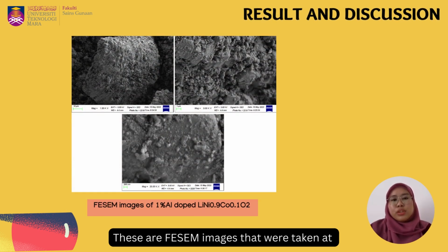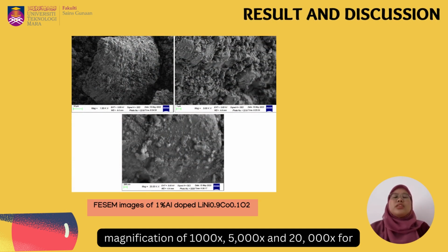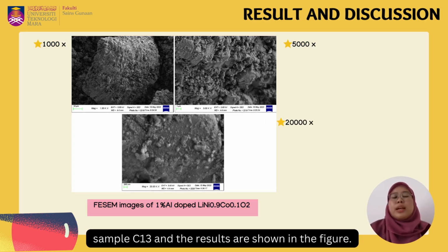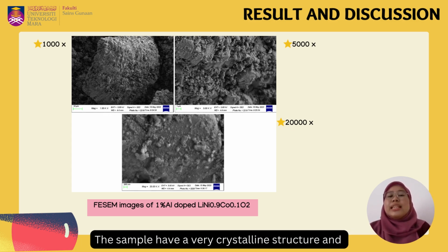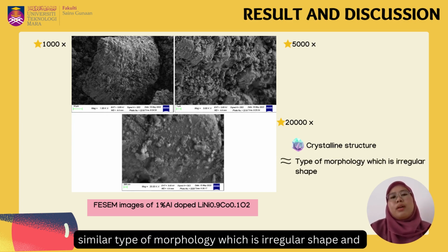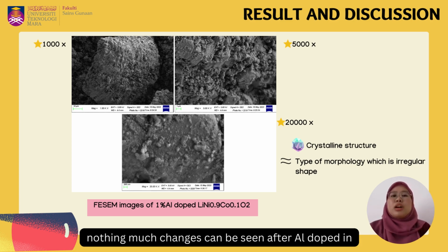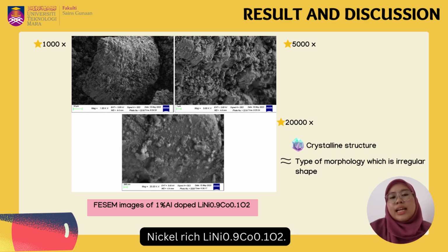These are SEM images that were taken at magnifications of 1000 times, 5000 times, and 20,000 times for sample C13, and the results are shown in the figure. The sample has a very crystalline structure and a similar type of morphology, which is an irregular shape, and nothing much changes can be seen after aluminium doping in nickel-rich lithium nickel cobalt oxide.